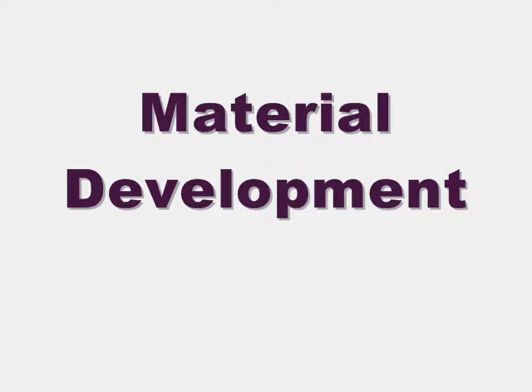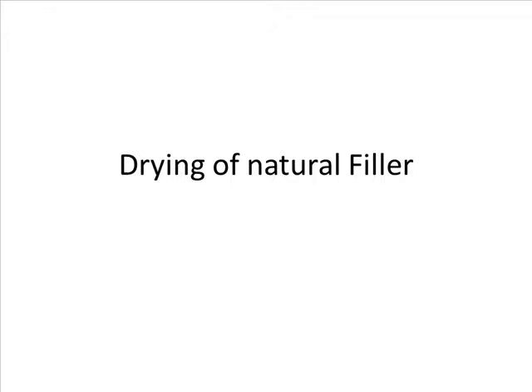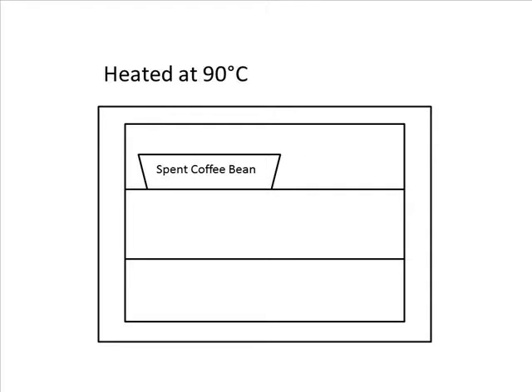Now, moving on to talk about material development. In this study, bio-composite materials were produced by compounding spent coffee beans with a polymer. Firstly, there is the drying of the natural filler. The coffee beans collected were heated in an oven to a temperature of 90 degrees Celsius for 2 hours to remove any moisture present before compounding.